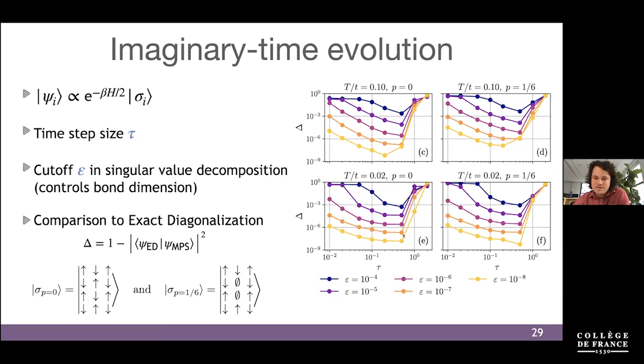And even for these larger cutoffs, we get like six digits of precision. So this is on the level of single precision, so it's almost like machine precision, if you want to call single precision machine precision. Nevertheless, what's kind of surprising is that we can take these long time step sizes. Here we think that the optimum is mostly at a time step size of 0.5. This is maybe a bit surprising for people who are used to the idea that if you decrease the time step size, it becomes more accurate. Well, if you decrease the time step size, you have to do more cutoffs, so it becomes less accurate. So it's a bit different than, for example, solvers for ordinary differential equations.